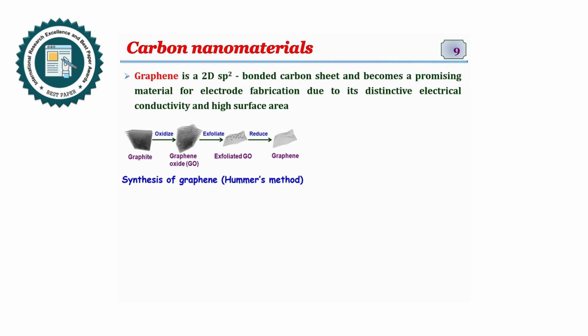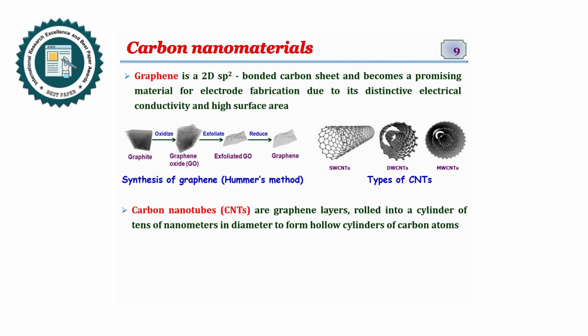Generally, graphene is synthesized from graphene oxide, which is synthesized from graphite by Hummers method. Graphite is oxidized to graphene oxide, exfoliation of graphene oxide leads to exfoliated GO, and reduction of exfoliated GO leads to graphene. Carbon nanotubes are another kind of carbon nanomaterial, which are graphene layers rolled into a cylinder of tens of nanometers in diameter to form hollow cylinders of carbon atoms. Different types of carbon nanotubes are available: single wall, double wall, and multi wall carbon nanotubes.